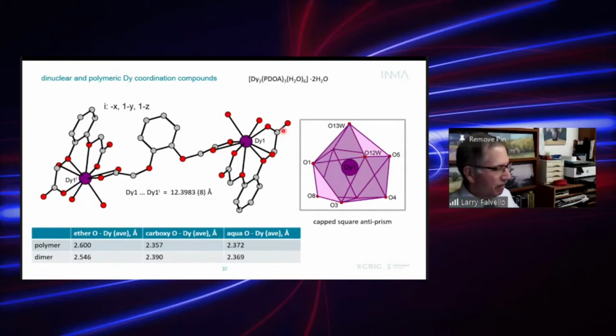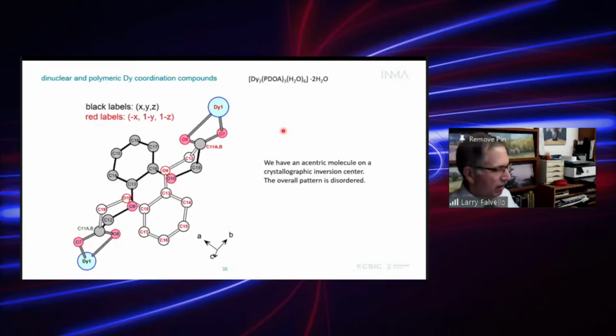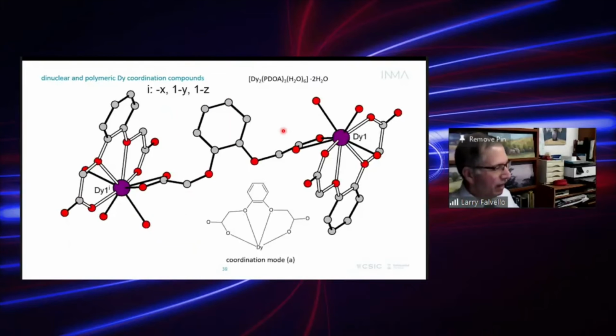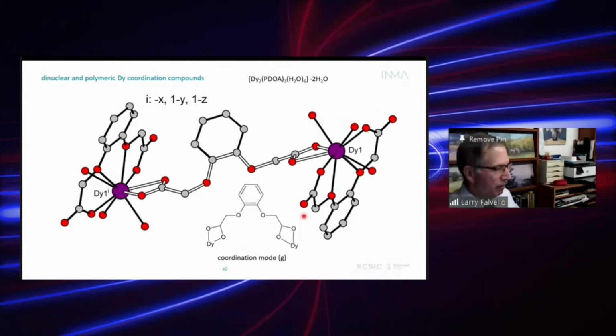And for the second dysprosium compound, one ligand is in the arms open mode. That is disordered about a center of symmetry. So right there we already lose some information if we measure a single crystal. And the other ligand is the blocking ligand that through its coordination mode blocks the formation of a polymer.